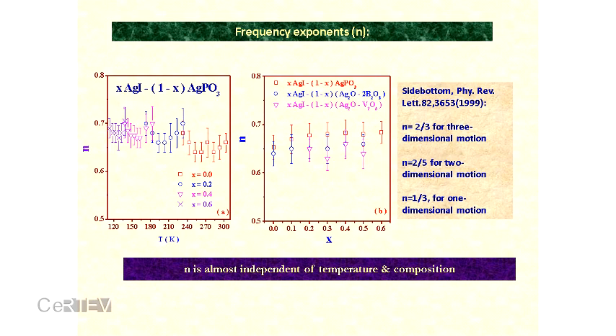But we have also shown that for mixed alkali glasses, the dimensionality of this conduction space goes from 2/3 to 2/5, and it is less than 2/3, as a consequence of which the conductivity is 2 dimensional. That is why when we mix 2 alkali, its conductivity is decreasing, because the dimensionality of the conduction space is decreasing. So this theory equally explains the mixed alkali effect also.